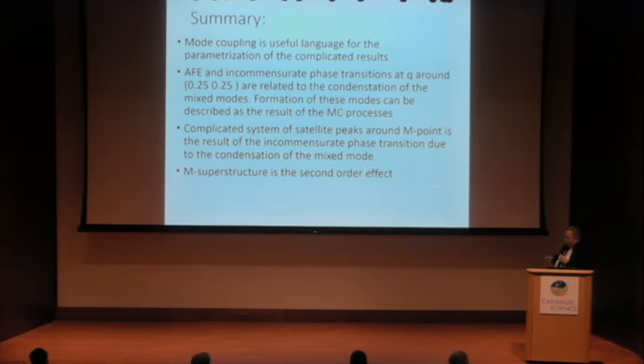So indeed, there is this ferroelectric phase. We actually confirmed it. We have a paper on piezoelectric force microscopy confirming that the phase is ferroelectric. But it is not rhombohedral. The fact that it's not rhombohedral is probably related to the coexistence of a rhombohedral distortion at the gamma point plus this incommensurate one close to the M point.